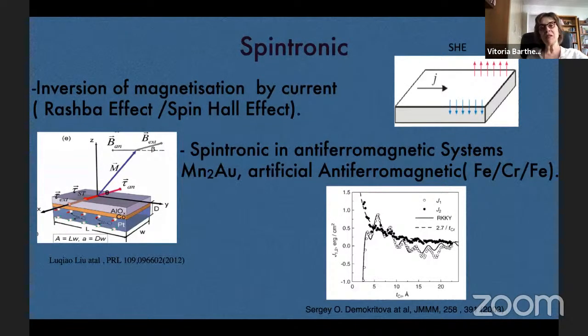The other aspect of our research is in spintronics. In fact, our focus is the inversion of magnetization by currents, because normally in a device, you change the resistance between R and zero by a field. And recently, you see that there are effects such as the spin Hall effect and the Rashba effect that can generate a polarization field that will turn the magnetization when the current is passed through the surface.